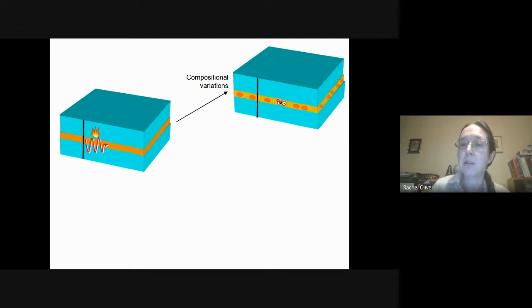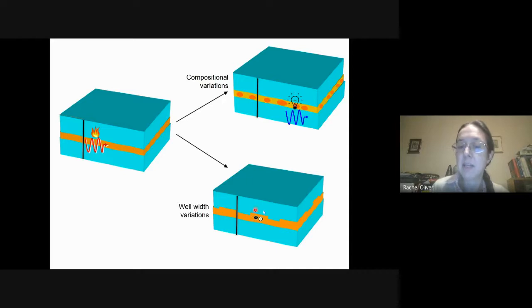The high indium content, dark orange regions, we might expect to have a lower local band gap. Electrons and holes that just happen to move to that region will be trapped in the high indium content, low band gap region. They won't be able to move smoothly in the plane of the quantum well. They won't be able to meet the dislocation. So when they recombine, they'll give out light, which is what we want. It's actually possible that rather than compositional variations, it could actually be thickness variations in the layer that is the quantum well that trap the electron and hole.